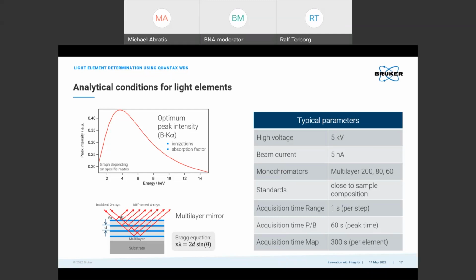And we can see that for the K lines of light elements, the fluorescence yield is very low. In fact, for carbon, the fluorescence yield is below 1%. So that means that less than 1% of the ionizations that are produced for a light element like carbon, for example, will produce photons.